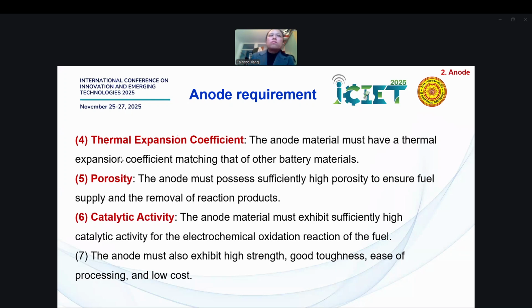And the anode must be porous, because we need all the gases to get through the pores and get into the reaction site, meaning the interface between the anode and the electrolyte. This ensures the fuel supply is enough, and removes the reaction products, like water produced at the anode. You can't go too high on porosity, because with high porosity you have less chance for connections, so you have to balance between the high and the small values. For porosity, we usually get 20 is a good number, or 20 to 30, depending on what sort of fuel you use.